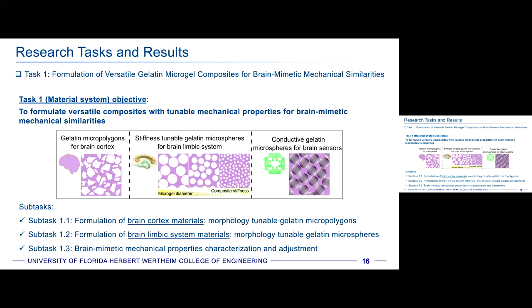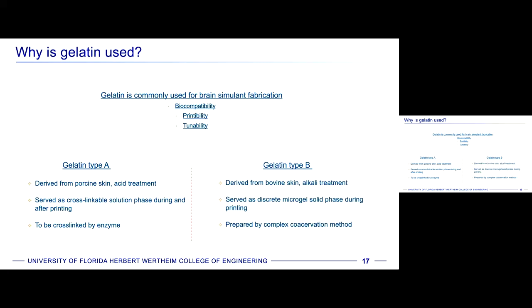The first is to create the homogeneous large volume brain cortex area. And the second is to develop a stiffness tunable gelatin microspheres so that we can match the regional stiffness of different regions of the brain in limbic system. And also we developed the conductive gelatin microsphere, and this can be used for brain sensors. So firstly, why gelatin is used for the brain simulant fabrication? It's biocompatible and it's printable so that we can use it with 3D printing, and it's tunable. So we can tune the mechanical property to match different stiffness of different regions of the brain.